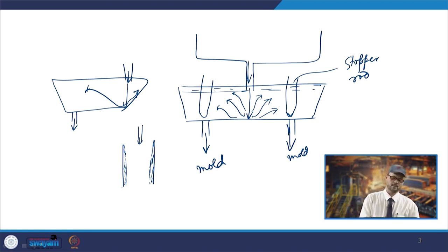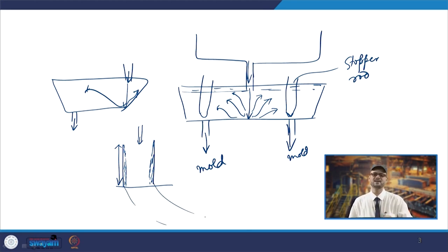Now, what should be the height of this mold? It has to be such that it ensures a skin of certain thickness is frozen, because the ingot has to further come down, move on the rollers, and finally move in the horizontal direction. There is a large amount of pressure of the liquid steel, ferrostatic pressure. So you ensure that cooling is such that a skin of adequate thickness is developed at the end of the mold. That is the requirement in the case of the mold.